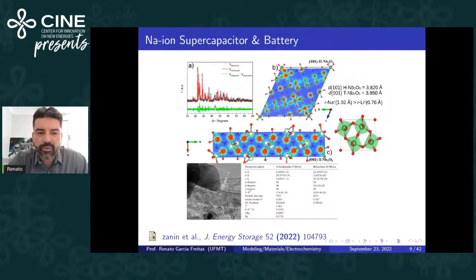So first of all, we performed the Rietveld refinement, as you see here. The Rietveld refinement is not well oriented, as you see here, because we have a decrease in the peak profile, isn't it? And we have two kinds of reflection for the sample. We have orthorhombic niobium oxide, like this part here, orthorhombic crystalline structure, and we have this phase as well, the monoclinic niobium oxide. So you see, here we have the 101 monoclinic niobium oxide, and here along this long b-axis, we have orthorhombic niobium oxide, isn't it?